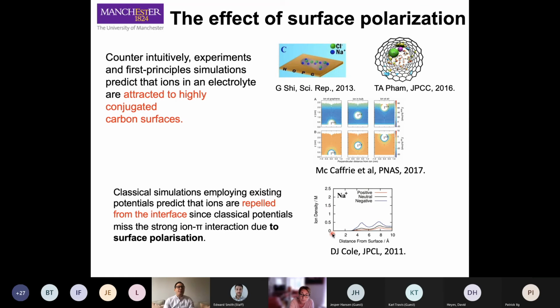So, for example, if you perform a simulation with the standard force field and you look at graphene with an electrolyte, this was again sodium chloride, I think, what you see, if you look at the distribution of the ions as a function of the distance from the graphene, is this depletion region. So ions are actually repelled from the surface and tend to stay well hydrated in the bulk.